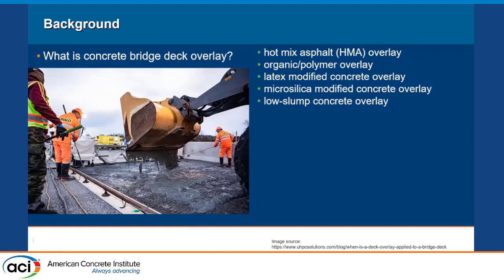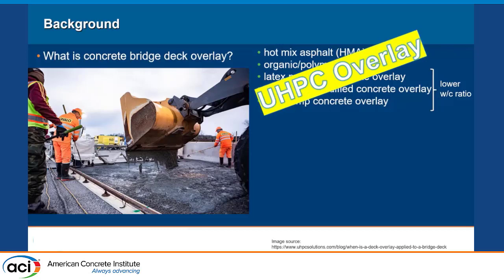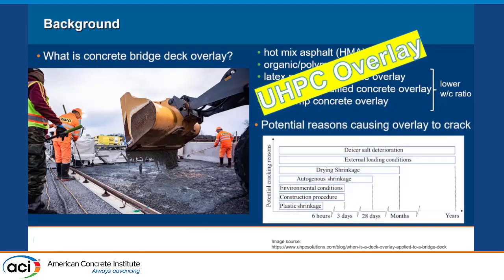So here are multiple types of overlay, and for the concrete-based overlay, usually it has a lower water-to-cement ratio, featuring a denser microstructure and a lower permeability to water and other deleterious ions. But right now, UHPC overlay is becoming increasingly popular throughout the USA, and even though the UHPC overlay features superior properties, we still need to be very careful of all these potential causes that lead the UHPC overlay to crack from time to time.